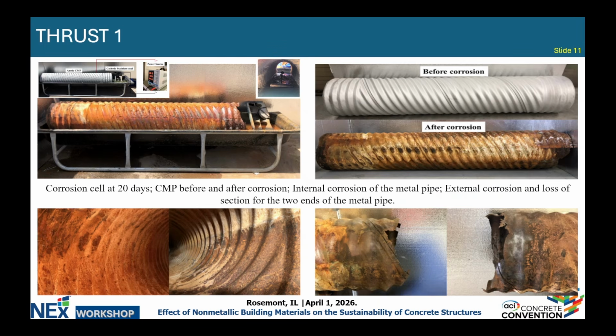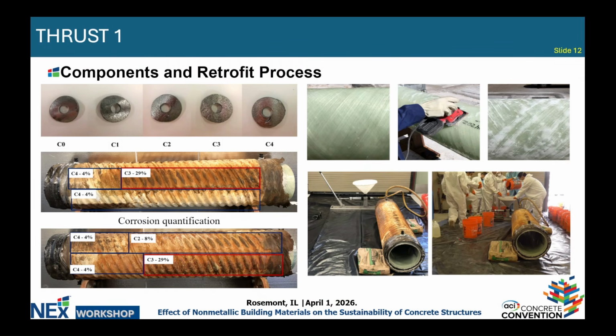which brings to our actual aging problem or the corrosion-induced failure problem. So this damage was created in the CMPs using an accelerated corrosion, very fast 20-day electrochemical cells. So you can clearly see the effect of corrosion after and compare it to the before picture, including interior corrosion developed with sort of a spraying effect, increasing oxygen levels inside. And you have this entire system now corroded. So you have an uncorroded system and a corroded system for comparison.